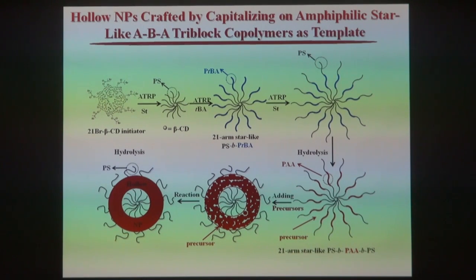now we can, first of all, design. Here, I regard this as an ABA star-like tri-block copolymer. So the outermost and the innermost blocks are the same, in this case polystyrene, and the intermediate block is poly(tert-butyl acrylate). So they are made by sequential atom transfer radical polymerization of styrene, tert-butyl acrylate and styrene. Then you convert this intermediate poly(tert-butyl acrylate) group into polyacrylic acid, PAA, adding precursors. So now this precursor only selectively segregates into the intermediate block, gets sequestered in the intermediate block, forming a hollow nanoparticle.